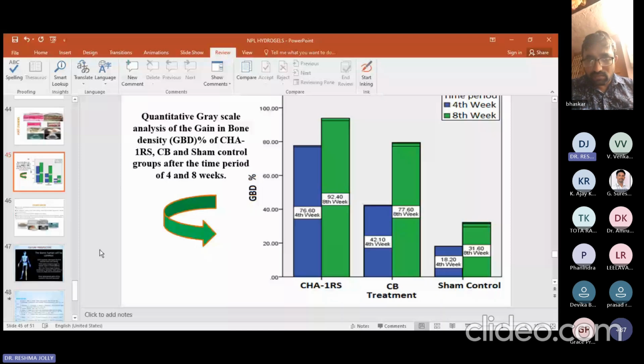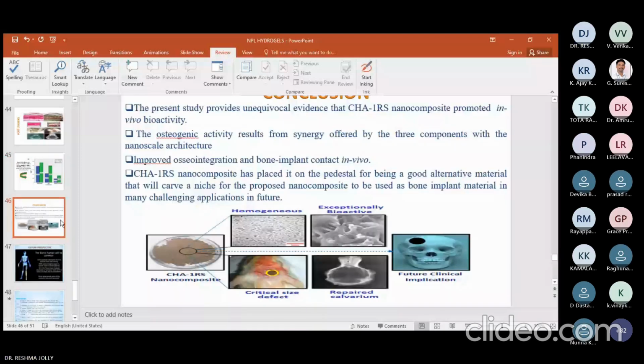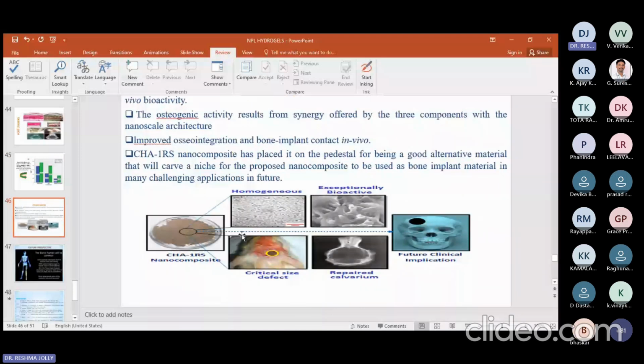So the conclusion we can draw from this study is that this material was quite bioactive. The osteogenic activity was improved, and the osseointegration and bone implant contact in vivo were improved. So this composite can be a good alternative material, because the clinical trials are still underway. So we hope that this material could play an important role to bring it from lab to industry.